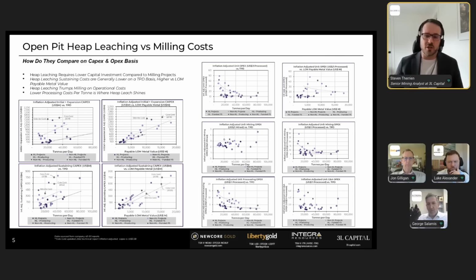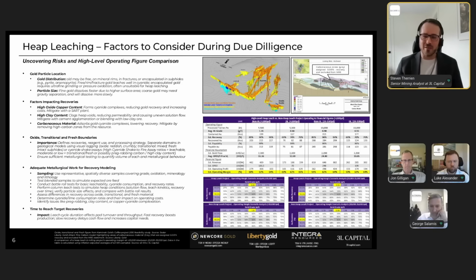The average strip ratio of the heap leach operations in the study that were lower than 20,000 tons per day had a strip of 2 to 1, while the milling operations had a strip of 5.5 to 1. And then you can see on the processing OPEX versus tons per day, this is really where heap leach shines. At 20,000 tons per day, heap leaching costs might average $3.87 per ton, and that's a lot lower than the average milling rate at $9.92 per ton.